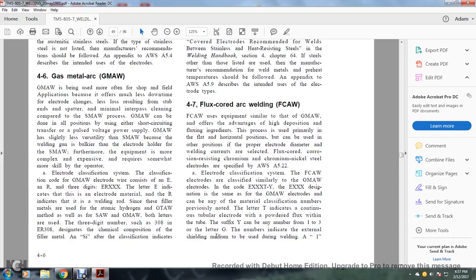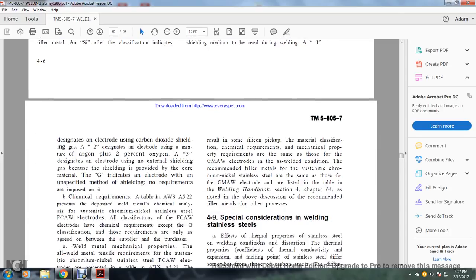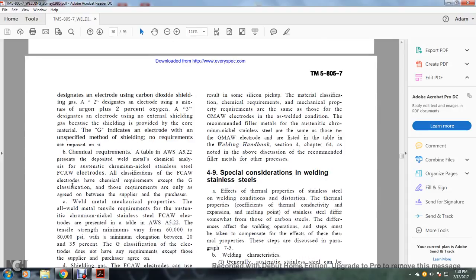The number indicates the external shielding gas to be used during welding. A 1 designates an electrode used with carbon dioxide shielding gas, and 2 designates an electrode used with argon plus 2% oxygen. 3 designates that the electrode has no external shielding, because it is provided by the core of the material. The G indicates an electrode with an unspecified method of shielding. No requirements are imposed on it.